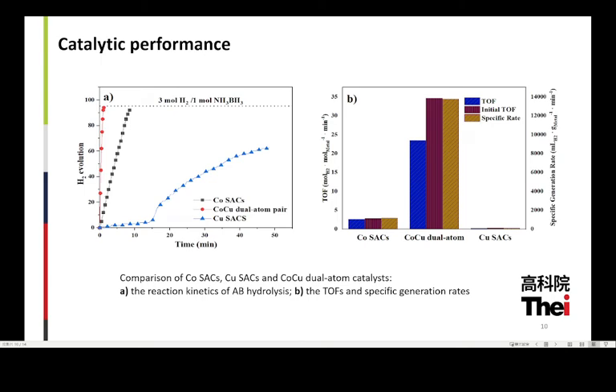In this part, there is an interesting catalytic performance. It shows that non-precious metal catalysts such as cobalt and copper, if they exist alone, the performance is not very good, but if they mix together, like cobalt-copper dual atom, it brought a synergy effect and showed a much better performance in reaction time, TOF, and specific rate.